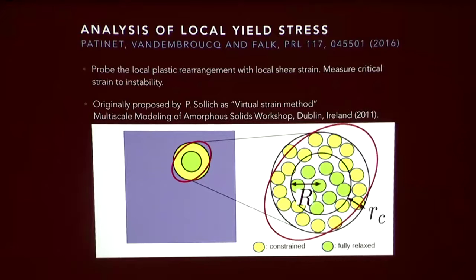We have to choose a length scale for that frame—how big is this region you're going to allow to deform inside the frame? There was prior work proposing that for this Lennard-Jones system, about 5 atomic diameters is the length scale on which you recover elasticity. If you're smaller than that, you don't really have Hookean elastic response, but larger than that length scale, you have inhomogeneous but basically Hookean elastic response.